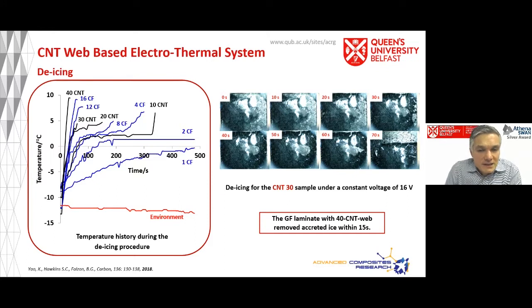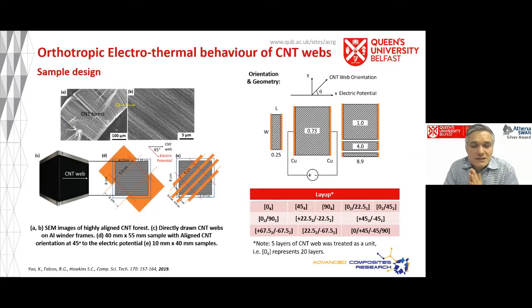Now, I mentioned earlier that these webs are tunable. And what I mean by that is, well, for starters, you remember how I talked about you can grow your carbon nanotube webs initially vertically as a forest? Well, you've already got two parameters that you can play with there to tune your conductivity. You've got the height of that forest, or the length of the CNTs, the aspect ratio of the CNTs. You can also control the density of that forest.